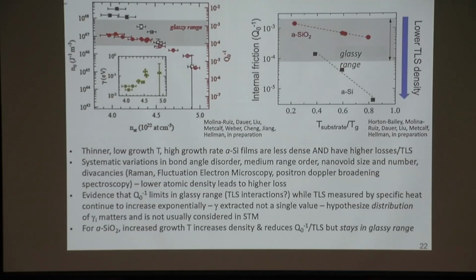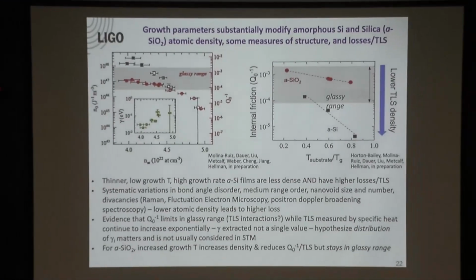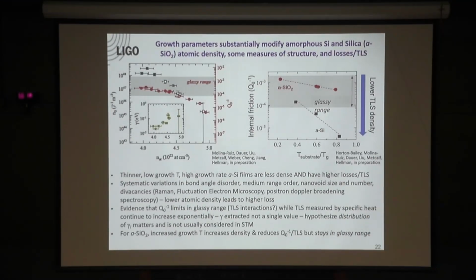It's sort of buried, as I said, I was kind of rushing by there. From measuring the heat capacity and the internal friction, we can derive gamma. And when you do that, first of all, it's not 1 eV. It's quite a bit below 1 eV, hence the comment, well, maybe it's 0.1 eV. But we've actually got numbers down at like 0.01 eV. And it changes with how we grow it. So none of this is making a lot of sense. So, I think this is going to force a reconsideration of what this means.